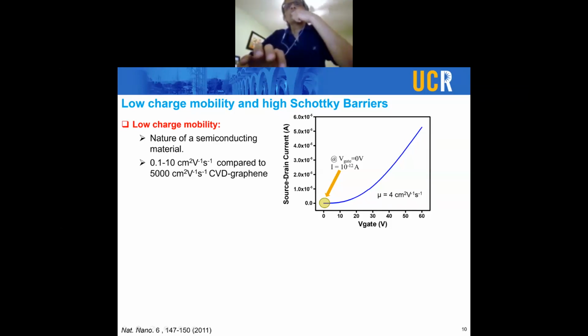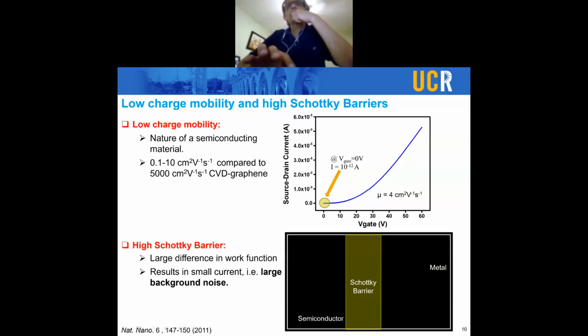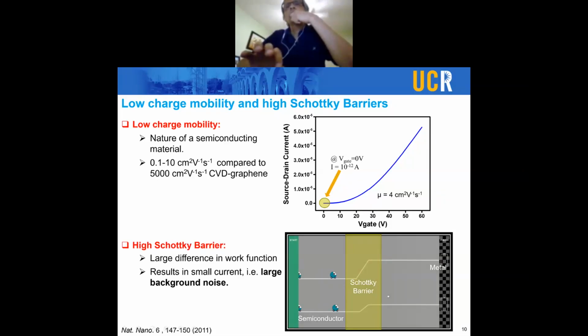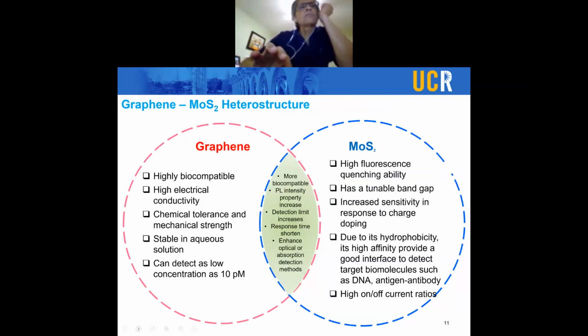And then also we have an issue with Schottky barrier, which is shown here when you have different work function materials put together, like which we'll have to do to make a device, because we have to put contact electrodes on the top of our MoS2 layer. So we were a little more cautious this time, and we decided not to jump in with both our feet into the testing of sensors based on MoS2 alone.